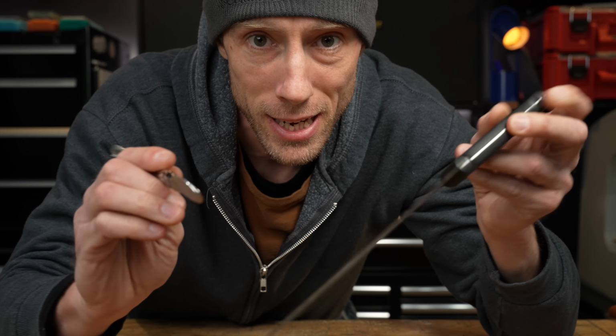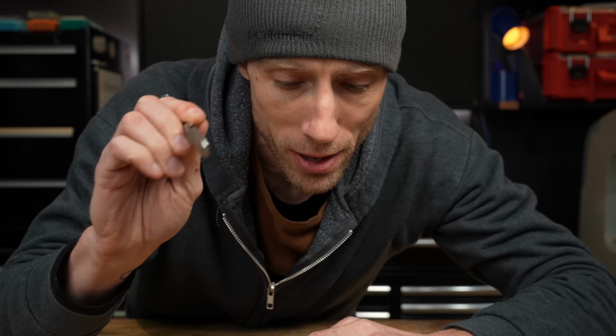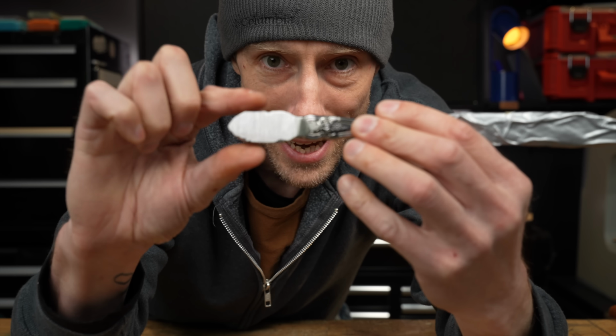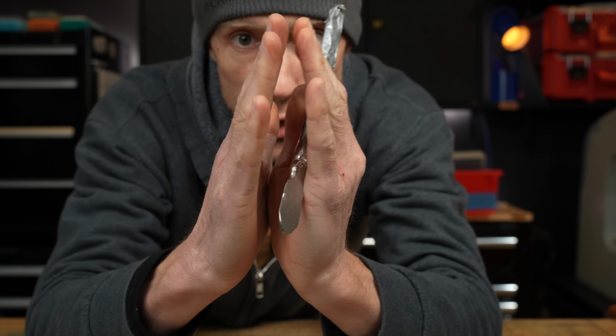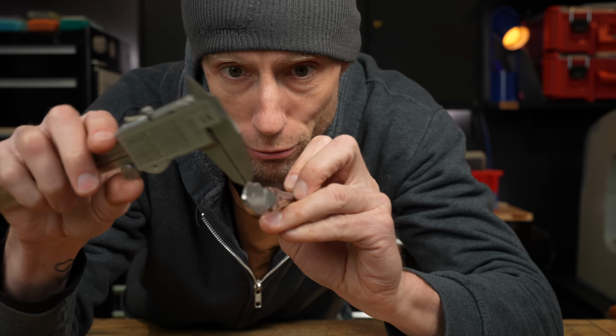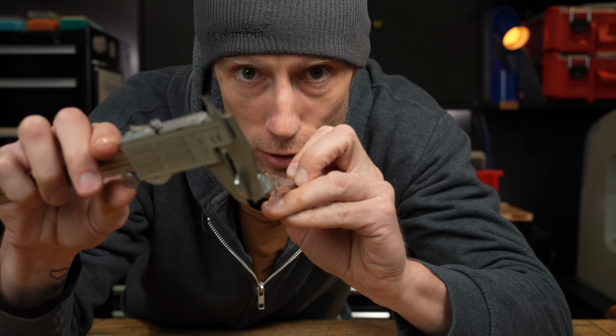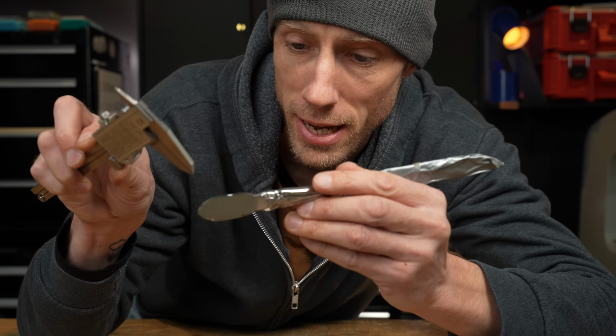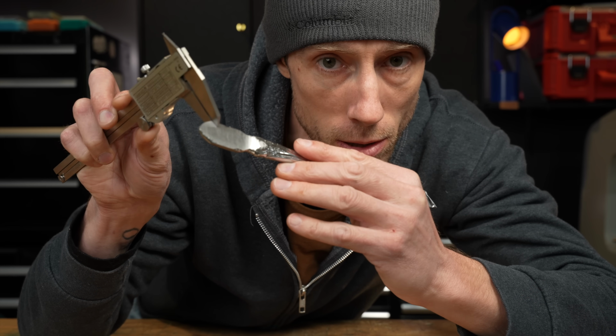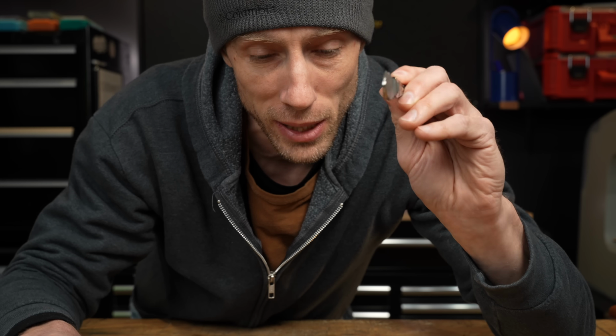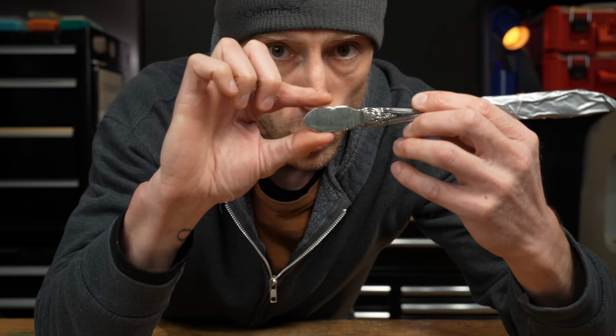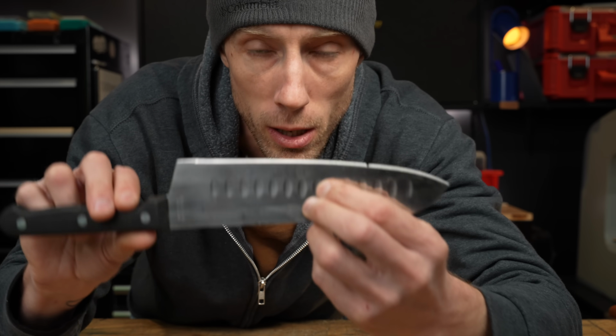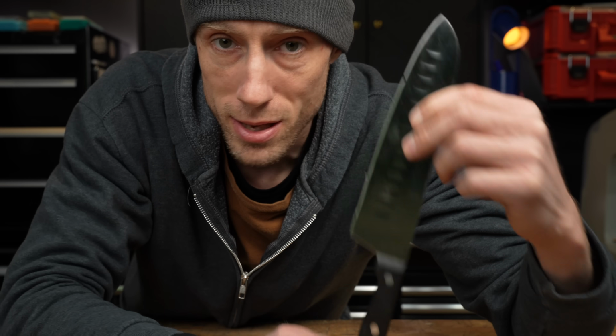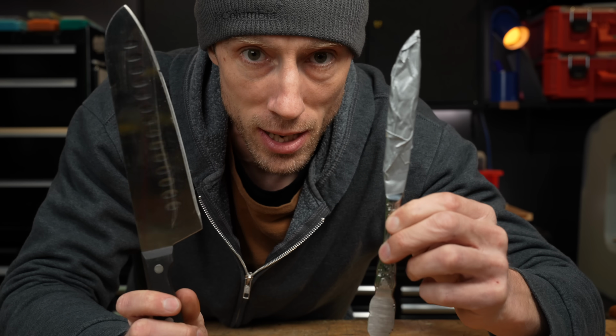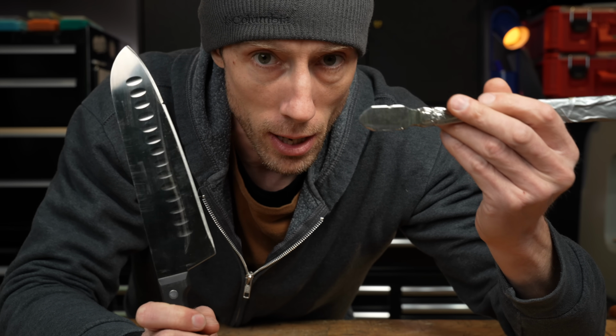Well, the thing here is that even though they have the same behind the edge thickness, our geometry on our butter knife is still thicker because our blade is actually shorter. So our wedge is thicker. It thickens up really quickly as we get farther and farther down the blade. If we do measure about 1/8 of an inch away from the edge of the blade, we're still going to have a thicker blade in our butter knife here because it's a shorter blade profile than we will on something like a chef's knife, which is why this knife is not going to survive at the same behind the edge thicknesses as our butter knife did.